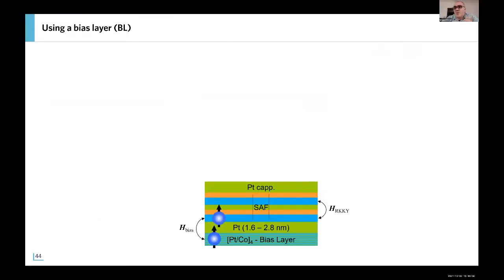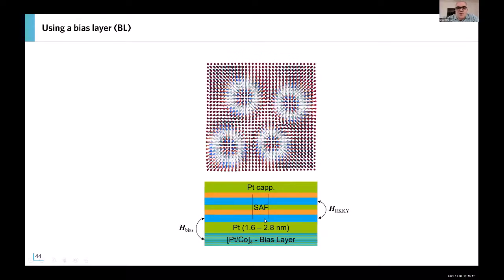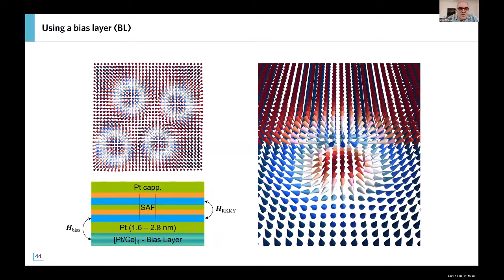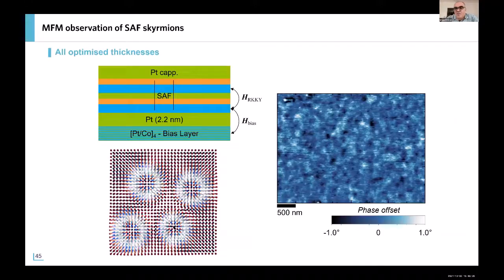But then we want to have antiferromagnetic skyrmions, not only spin spirals. And for that, we integrate again this bias layer, symmetric platinum cobalt platinum, in the systems in order to create this effective magnetic field that will be felt by the bottom layer of the SAF. And doing so, we can predict by simulation that it will transform the spin spiral into antiferromagnetic skyrmions. And this is what we, in fact, did, and we demonstrate, again, by MFM images at room temperature under vacuum. This is, to my knowledge, the first observation of antiferromagnetic skyrmions. These are these black dots here.